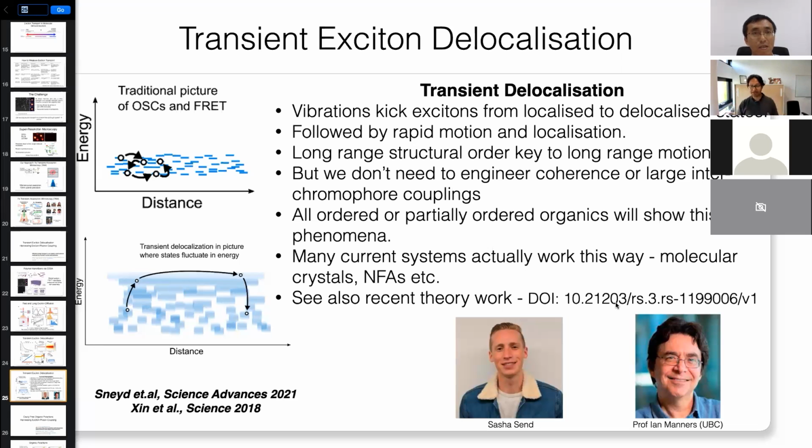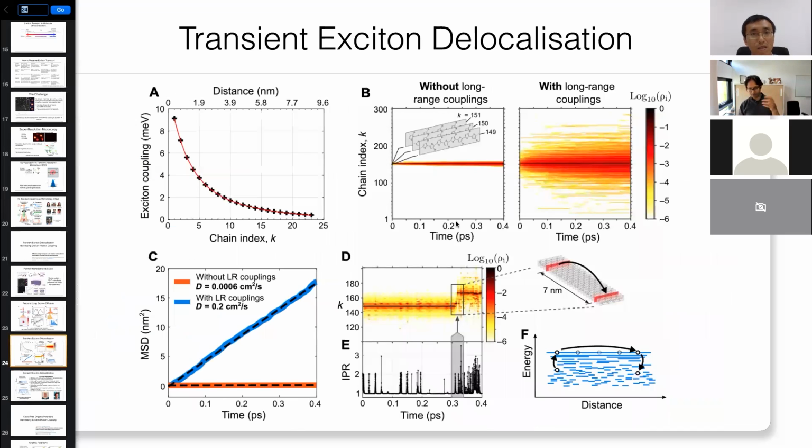And you can actually never get rid of it. It's always there. So that I think is the answer to how you do this. For instance, as part of this paper, I don't have a graph here, but we've looked at the ultrafast Raman, and we can see very clearly the singlet exciton is coupled to these high frequency 1450 wave number modes, which are oscillating the energy in time. And that always happens basically.